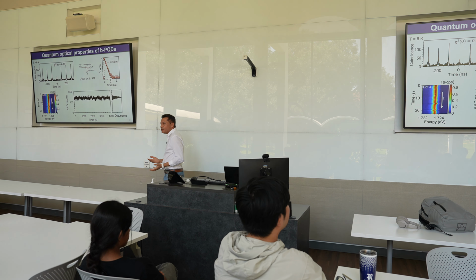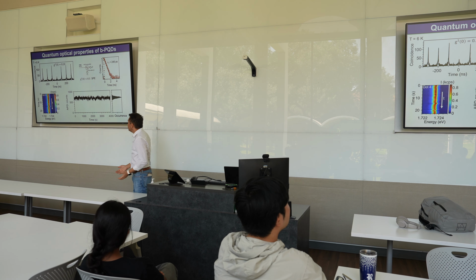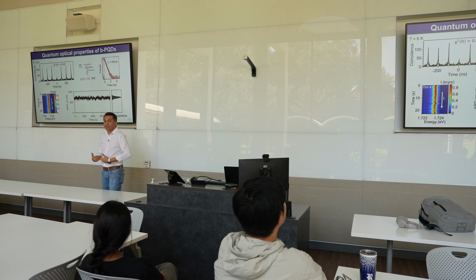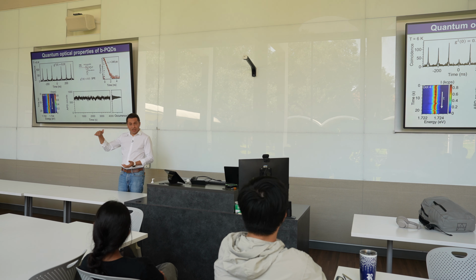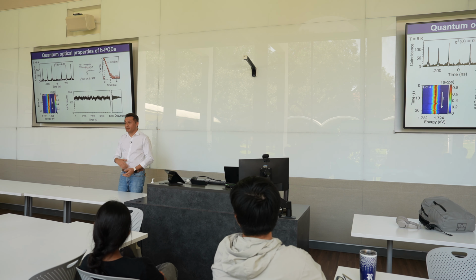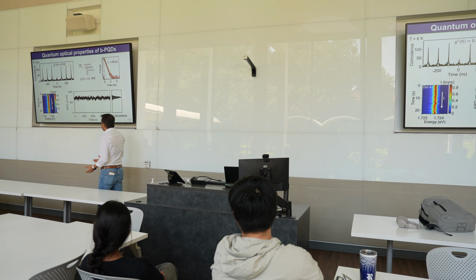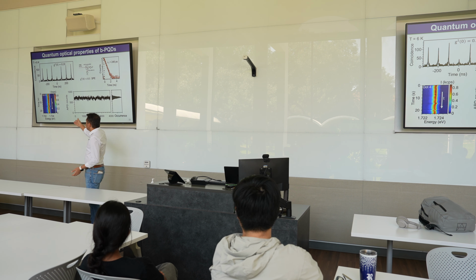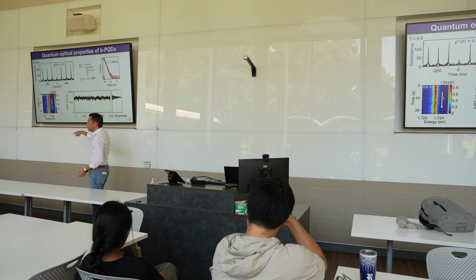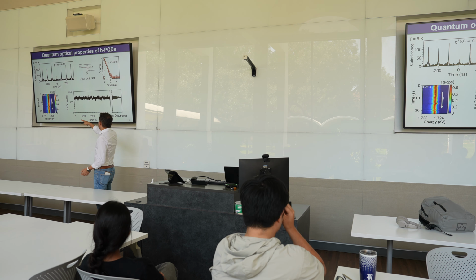They are not susceptible to doing chemistry on the surface. So you can see, that's your g2. The g2 is about 0.1. If you have a g2 signal below 0.5, that means you have single photons coming out of this. And look at the stability. They're extremely stable. You don't see any blinking or bleaching of these systems. We also measured this over 4,000 seconds. That's an enormously long time for this type of measurement.